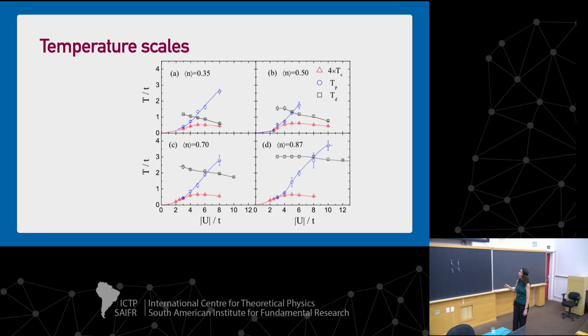So we just looked at it here once again to obtain a more detailed phase diagram. For each density, it looks a little different. This is the pairing temperature in blue. The red dot is 4 times the superfluid temperature, because it's very small, so if we don't multiply, you can hardly see. And here in black is the degeneracy temperature, which goes up and down a lot with density.